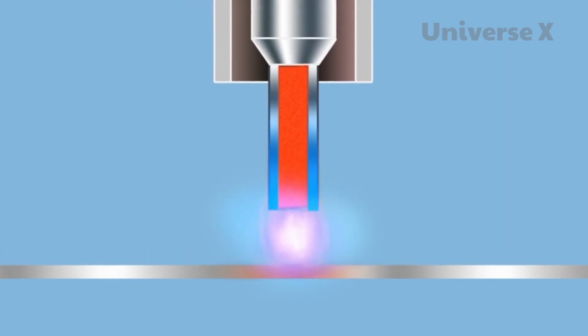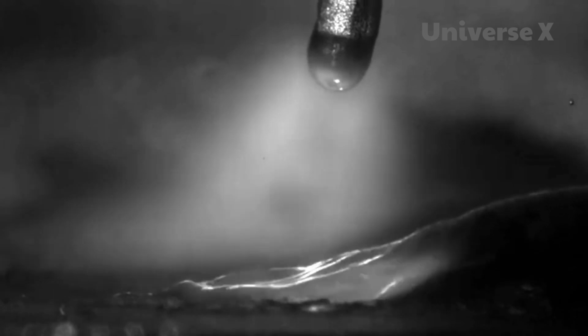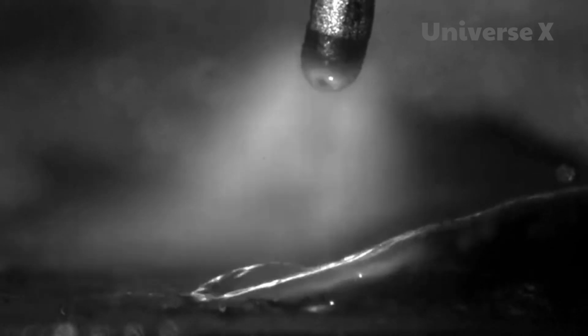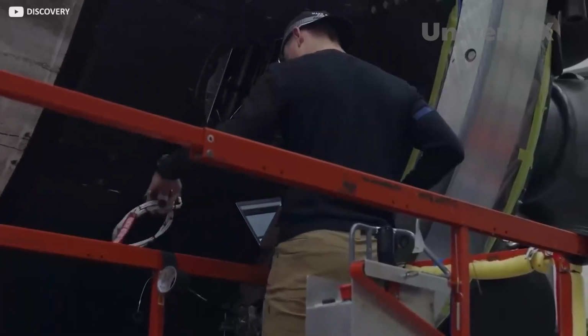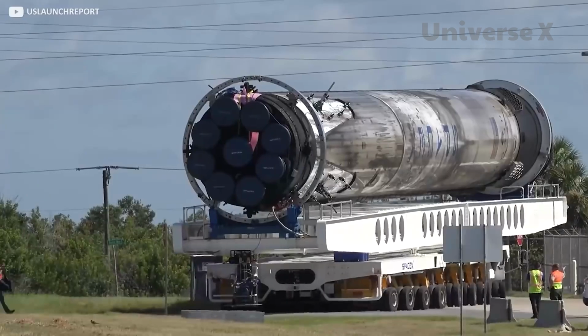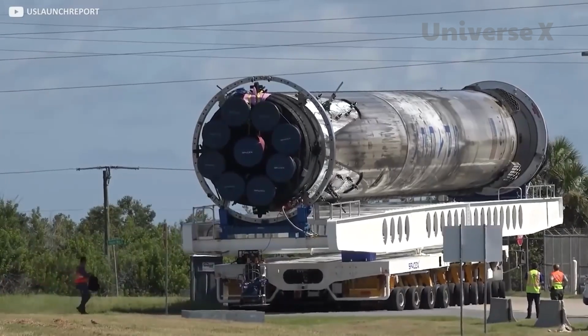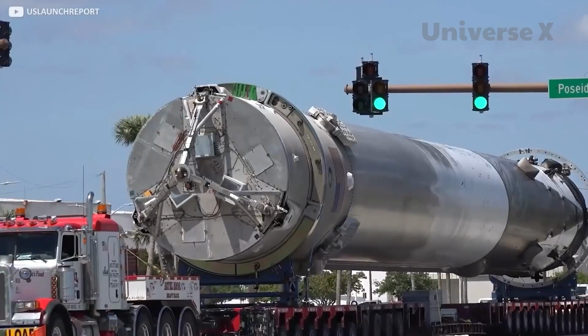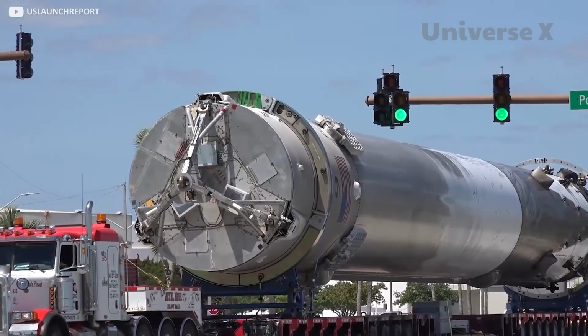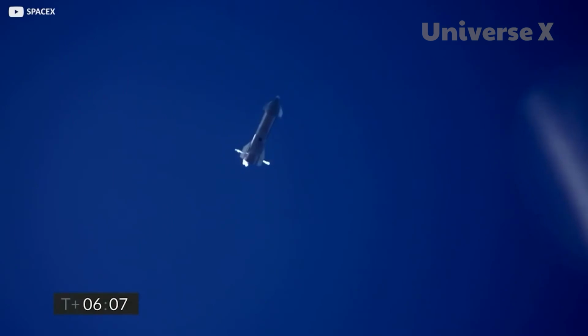The sharp edges and tiny cracks on the surface acted as pressure points, which could lead to larger cracks when the Starship was pressurized. By grinding the surface, these defects were removed, reducing the likelihood of weld failure. In theory, each weld should be as strong as the surrounding metal. However, the initial Starship test proved that this was not the case.